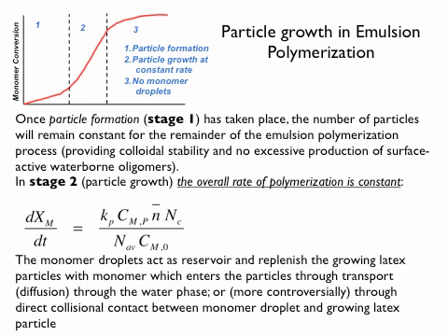So you get kp, the rate coefficient of propagation. Particles grow, which basically means the predominant amount of monomer gets consumed inside growing particles. Therefore, we need to know the monomer concentration inside the particles. That's important, so that's [M]p. And then n bar is a new kind of entity, which is the average number of radicals per particle. So this is a number.